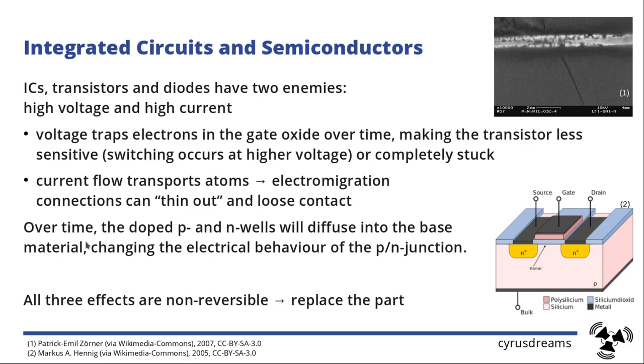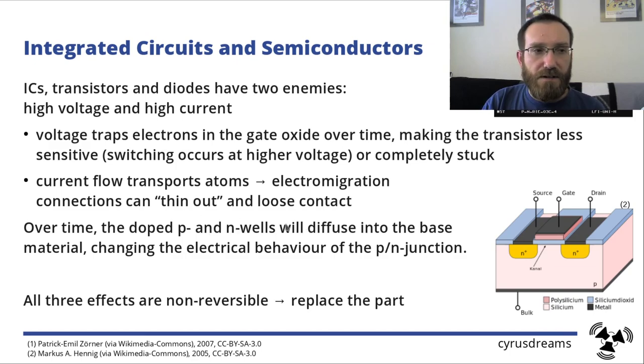You do have a third damage happening in integrated circuits. That is the diffusion, which means that the N-well, so there is doping in the silicon, so you have phosphorus, for example, implanted here. And there's a natural law that says that everything wants to be equally distributed here, the diffusion law, and that will make the N plus diffuse into the P over time. And that is changing the electrical properties of the PN junctions, and at one point in time the transistor will not work anymore because there's no usable PN junction anymore.